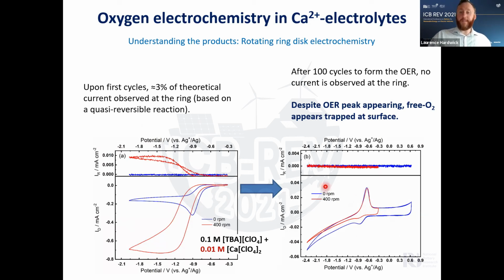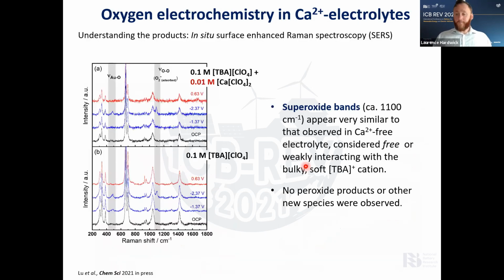But when we have this reversible process, when we look at our ring electrode, we don't see any positive current. So whatever's forming at the electrode surface is trapped at the interface, remains at the interface, and is not able to then go into the electrolyte to be oxidized at the ring electrode. We then did surface enhanced Raman spectroscopy to understand what species are forming at the electrode surface, and what we see is again the formation of oxygen superoxide and a gold oxygen interaction, which indicates that the active species at the interface is this superoxide.